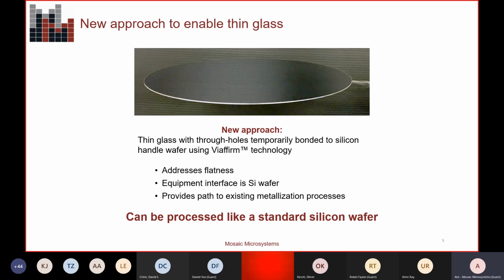So the whole idea of this approach is to make the thin glass look as much like a silicon wafer as possible to really eliminate the barriers to entry for high volume manufacture of glass substrates. So the carrier not only addresses the flatness, right? Now you have the stiffness of the silicon wafer. The equipment interface is a silicon wafer, so all the sensors embedded into the volume equipment that are used to sensing silicon will still be sensing silicon. And the physical interface to the vacuum chuck or the electrostatic chuck is a silicon wafer, so much less concern about putting multi-component glasses up against the equipment.